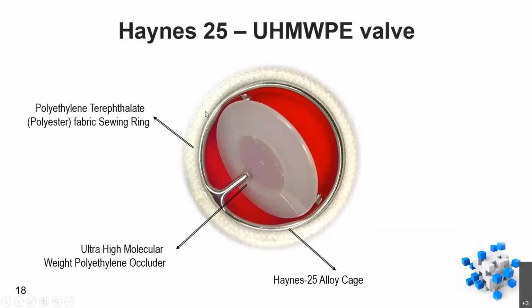And this is the current model of the valve which is in the market. We have this metallic portion made from Haynes 25 alloy, which is an alloy of cobalt, chromium, and nickel. The high molecular weight polyethylene is a polymer material. Then we have this fabric made of polyethylene terephthalate. This is the common polyester that we use for our dress materials. These are hand sewn to form this particular shape. And this suture ring, we call it a sewing ring, is used for stitching the valve onto the muscles of the heart. Slowly the muscle tissues will grow into this fabric and a nice joint will be formed.